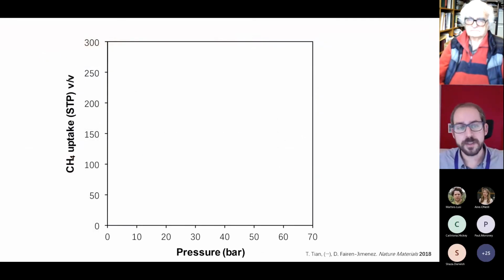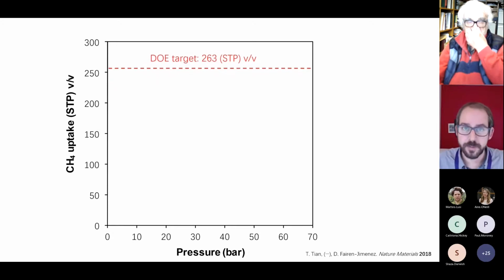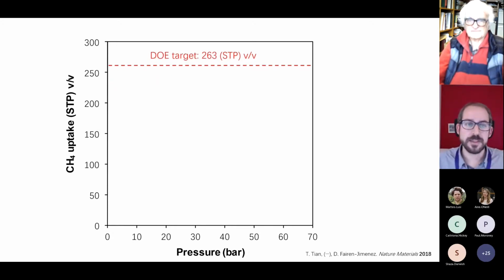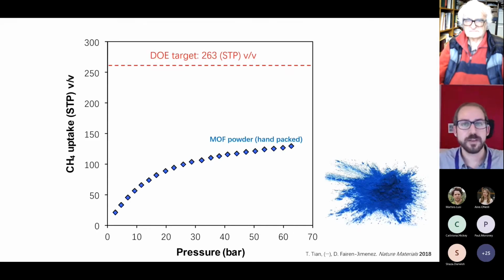To show this idea, this is something we published a couple of years ago in Nature Materials for methane storage, just experimental data, no simulations here. This is the Department of Energy target, and this is the pressure. So we try to compress the gases, and this is the best material that we were able to find in the literature, including activated carbons, metal-organic frameworks, anything. This is a material from Professor Omar Farha, HKUST-1, very far away from the Department of Energy targets, but extremely high capacity for methane storage.